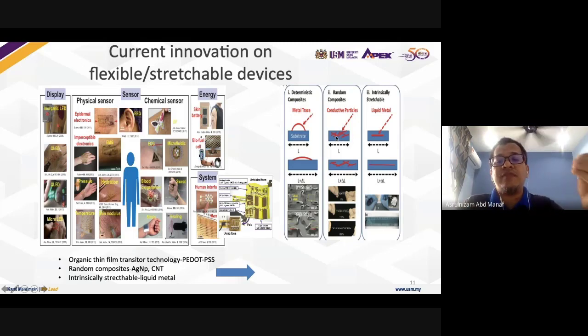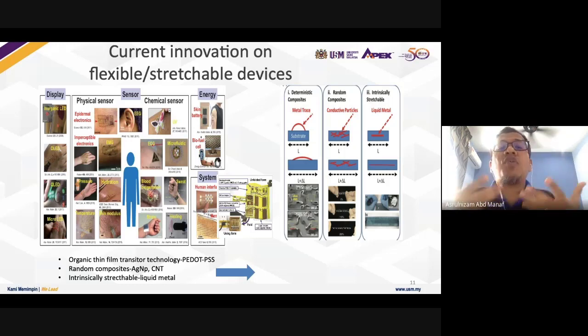I mean, in the ink formulation we use a polymer like PDMS or PPS, but we can mix it with the conductive particles, but we must ensure homogeneous mixing, so that we can have a conductive polymer. So when you stress it, it can also conduct electricity, right? And then the third technique they call the liquid metal,